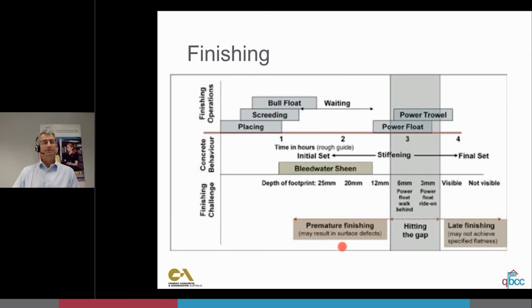What happens if we finish prematurely and we work this bleed water sheen into the concrete? Remember when we spoke about water cement ratio? If we add more water to the concrete, the water cement ratio increases and the strength decreases. If we work this bleed water sheen into the concrete, or if it rains and we work rainwater into the concrete, we're going to get a very weak surface on the concrete, and that'll show up as a dusty surface. So we want to wait for that bleed water sheen to evaporate and for the concrete to stiffen.